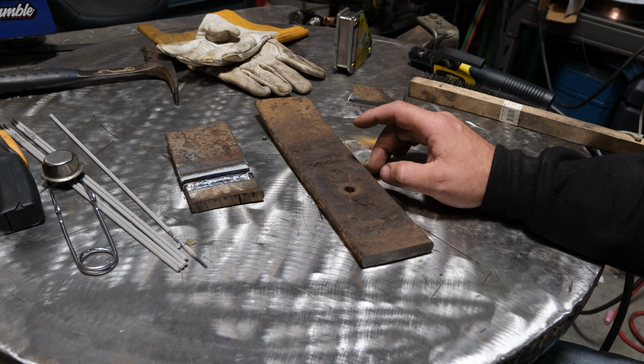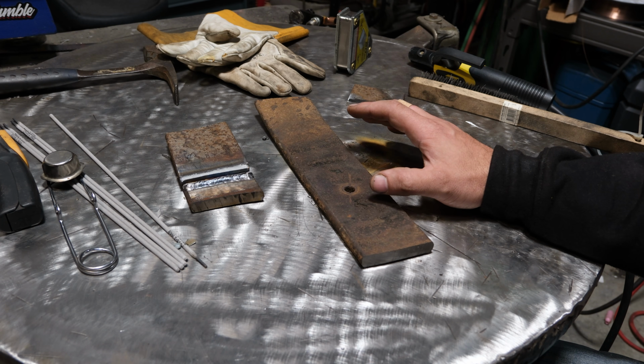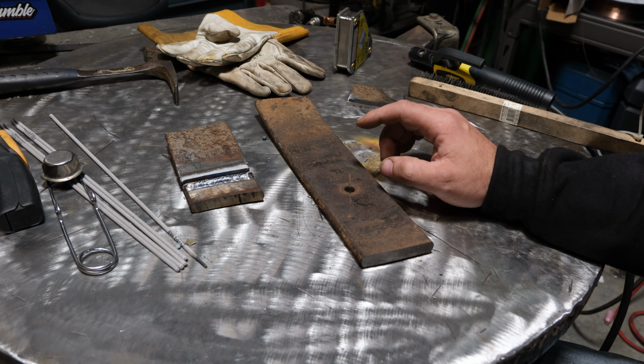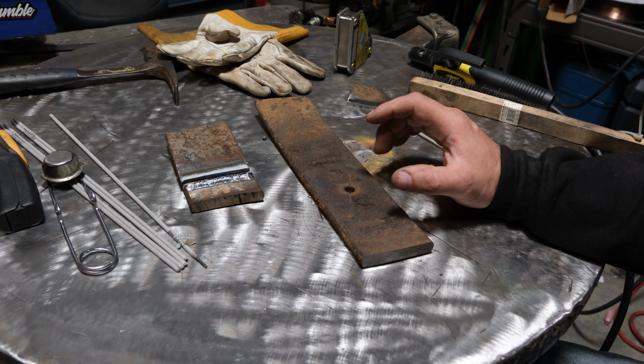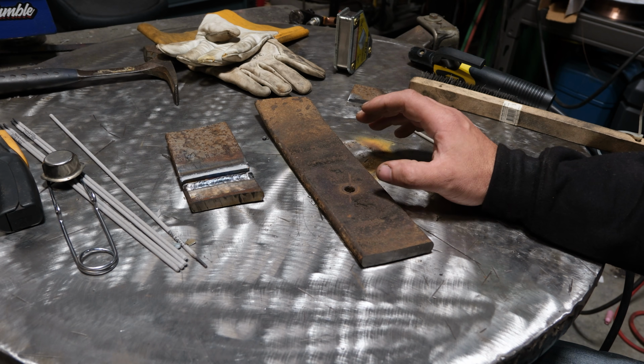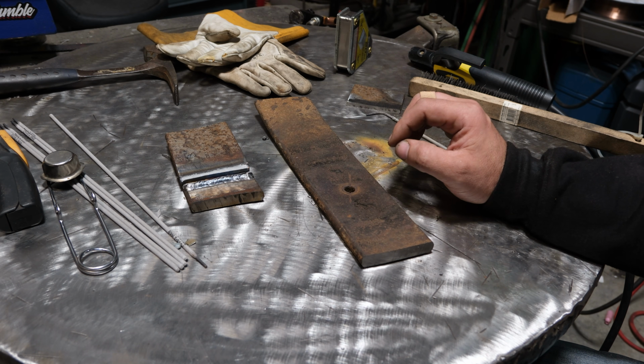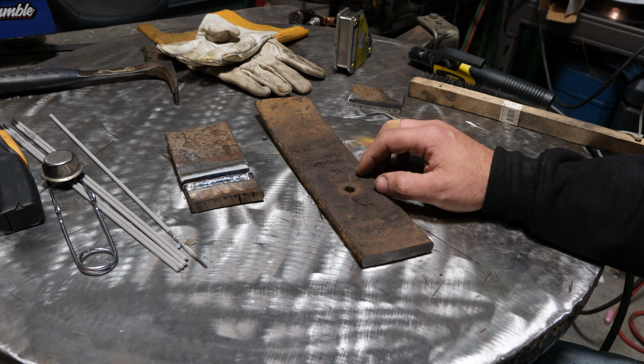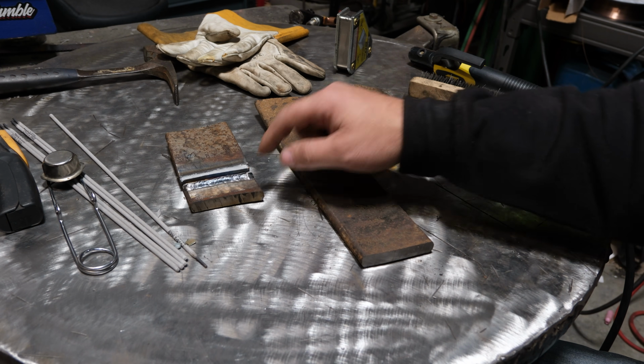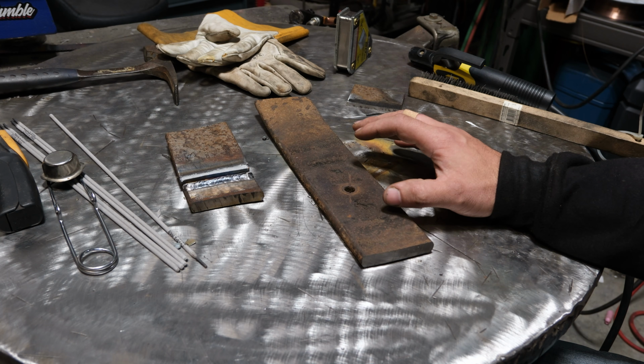One is to preheat the material to about 1,000 degrees, then weld it. Odds are that that would provide a solution. However, in my experience, when I've done that, I seem to have more failures with the base material, just like you saw in this, than what I'm going to show you.